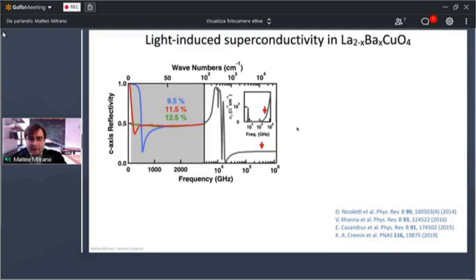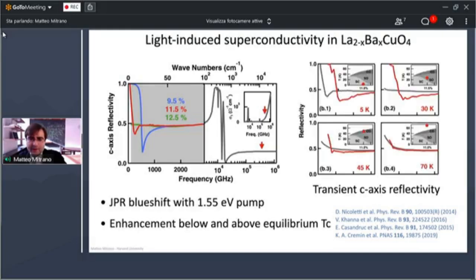We can see in this material, in the Cavalleri group, there have been reflectivity studies in which you start from a state where superconductivity is either suppressed or absent. And by shining laser light at 1.5 eV, it was possible to show a blue shift of this resonance, corresponding to an enhancement of tunneling along the z axis, both below and above the superconducting Tc. So this phenomenon can possibly be understood in terms of a competition with another order